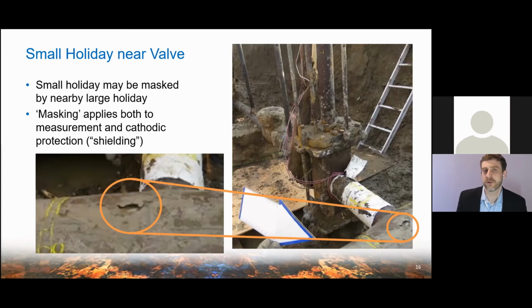So the valve may not be fully protected, but you don't really necessarily care if the valve is slowly corroding. It's very thick. It's got effectively a very, very long life. However, if you had a coating defect nearby and you're unprotected, that could be problematic. So that's going to come down to an interpretation thing. You need to understand very well what the data is telling you.